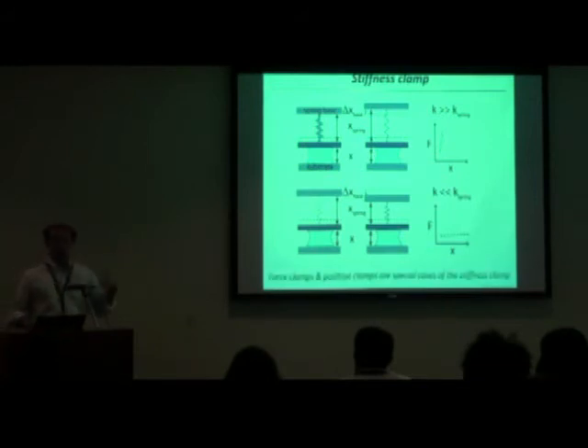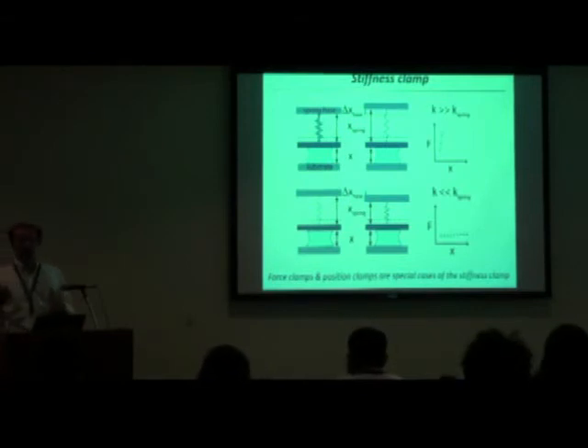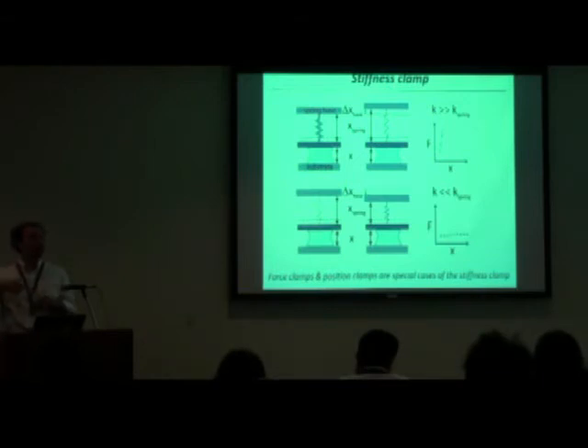And so we worked out how to do that. The basic idea is that, as I mentioned, to make something appear stiff, move away as it's pulling, and to make it appear soft, move with it as it's pulling. And then you've got the ability to vary your stiffness over a wide range. Interestingly enough, force clamps, which are routinely done in AFM and optical trap and other types of measurements, are just an extreme in one direction. A force clamp is a very, very soft surface because you have no way of increasing force. You can displace all you want. You don't increase force. And a position clamp, you can pull all you want. You don't change position. That's an infinitely stiff surface. So you can get a full range of stiffnesses from a single cantilever.